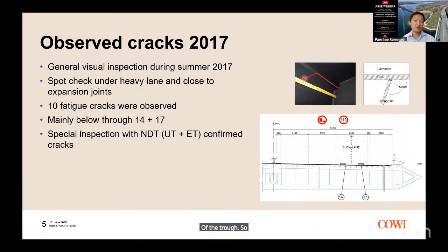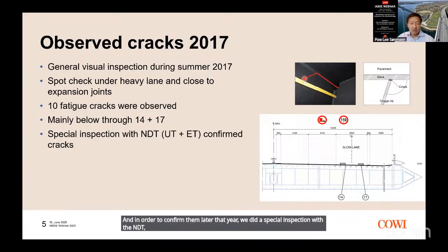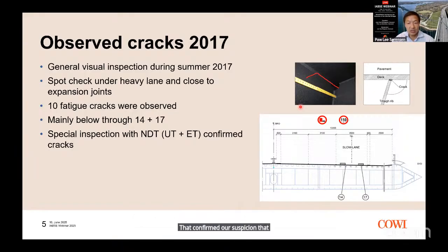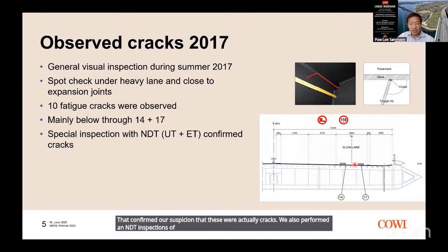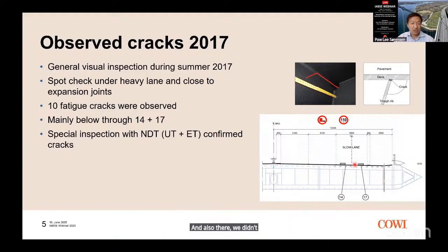So these cracks were observed by visual inspection, and in order to confirm them later that year, we did a special inspection with the NDT, UT and ET that confirmed our suspicion that these were actually cracks. We also performed NDT inspections of areas where we haven't seen cracks by visual inspection, and also there we didn't observe any cracks with the NDT. So this is of course quite alarming, to observe fatigue cracks.